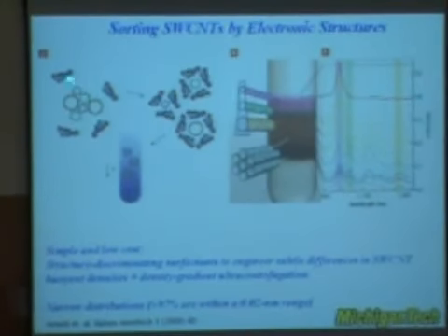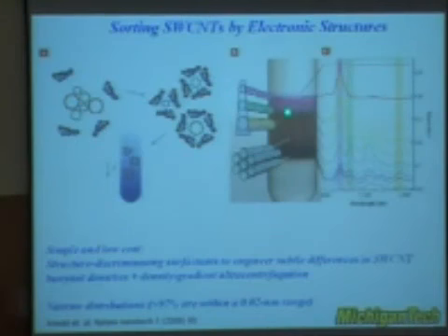They can use some surfactants that will adsorb on carbon nanotubes of different diameters. You can see that small diameter tubes have fewer molecules, and bigger diameter tubes have more, denser molecules adsorbed on them. So in this case, you will create nanotubes that settle at different densities if you do the centrifugal process, right? This is a very interesting work going on.